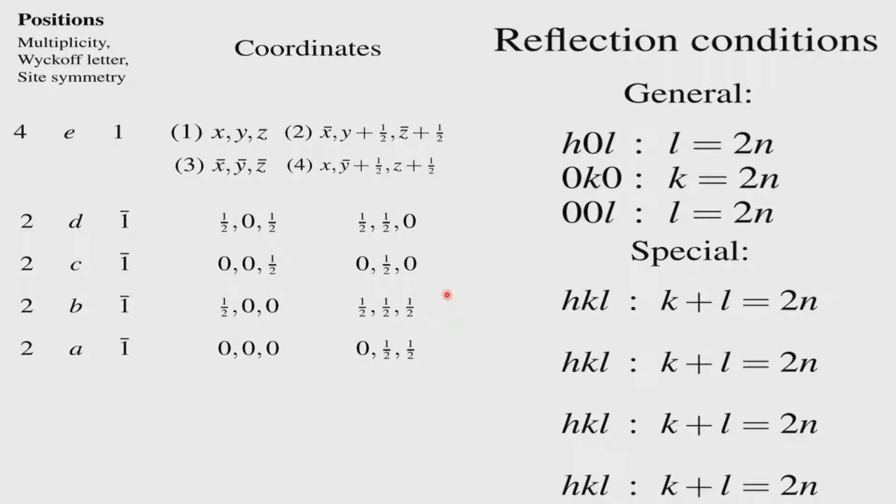So, when we are analyzing a crystal system like P 2 1 upon C, we first look at these absences. Even if the atoms or molecules are associated with this special symmetry, then we will get additional special absences. So, in general P21 upon C can be uniquely determined by just looking at these systematic absences.